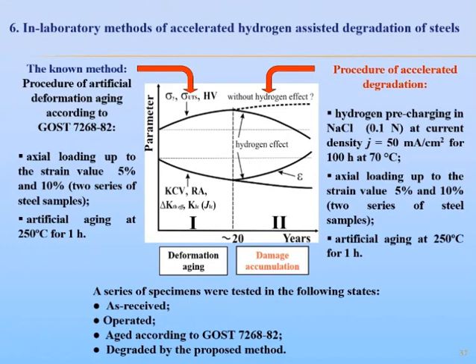Here it should be mentioned the existing method of laboratory deformation aging of structural steels, which consists of axial loading up to a strain value of 10% and artificial aging for 1 hour. Such a procedure provides deformation aging due to formation of Cottrell clouds which block mobility of dislocations. This corresponds to the first stage of material degradation when strength increases whereas plasticity and brittle fracture resistance decrease.